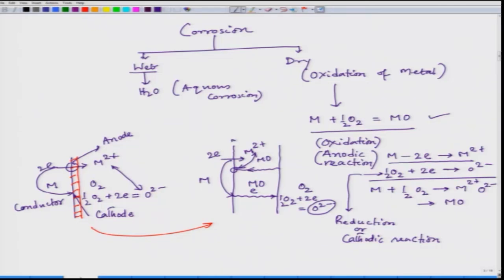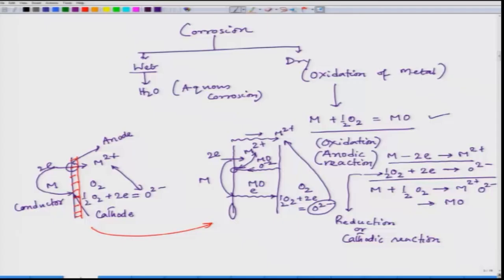Now, if the metal ion is moving on the outer side, and there this particular thing can combine and form metal oxide. Now, interestingly, charge flow is taking place through this. For example, here O2- is flowing, or here M2+ is flowing through this. So, charge flow is taking place through this MO. So, now MO becomes my electrolyte. In the case where oxygen ion goes through the metal oxide and reaches the metal surface, and at the interface of metal and metal oxide, further oxide molecules are forming, the oxide growth is taking place on the metal surface.